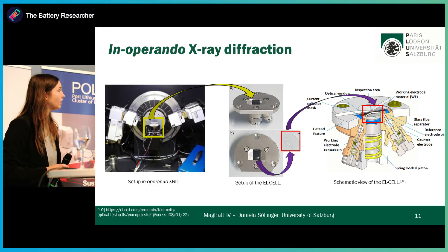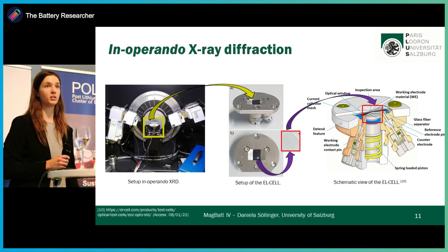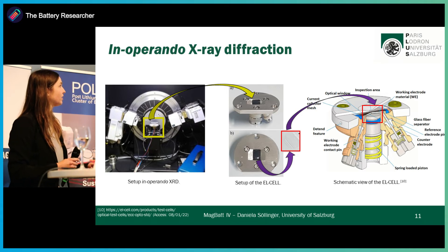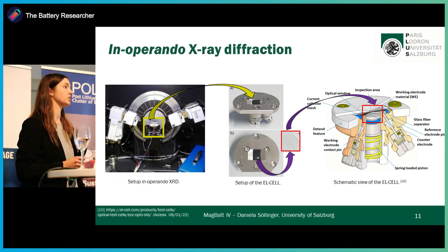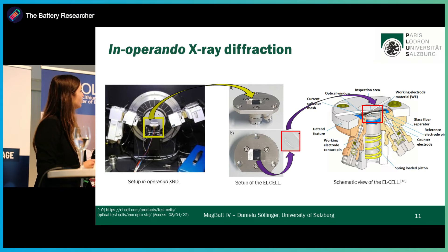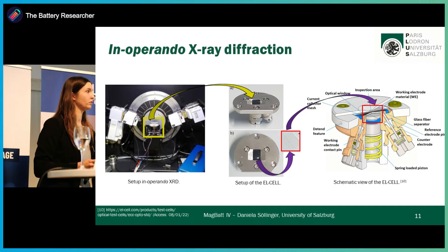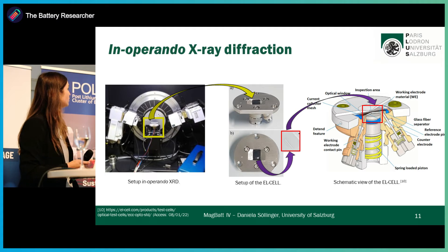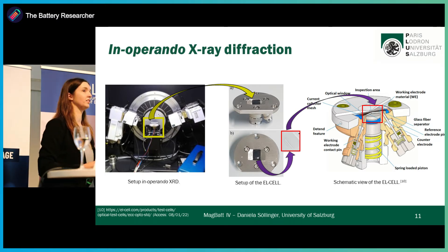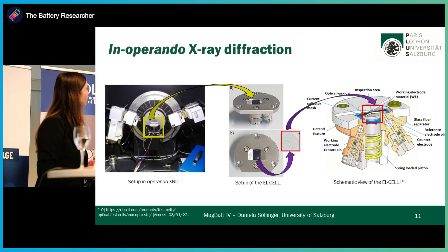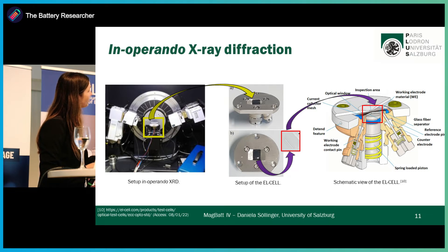Let me show you our setup for the operando XRD measurements. Through operando XRD measurements, we are able to measure the structure simultaneously to the electrochemical discharge and charge process. This allows us to see how the structure changes through the intercalation of different ions by use of different anode materials or different electrolytes, and should hopefully lead to an improved understanding of the intercalation mechanism. The setup of the cell is similar to the normal battery cell, but a hole is needed for the incoming X-ray beam. To ensure the cell is still airtight, we need an optical window, which is placed here during our measurements.